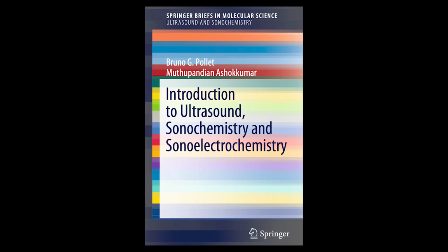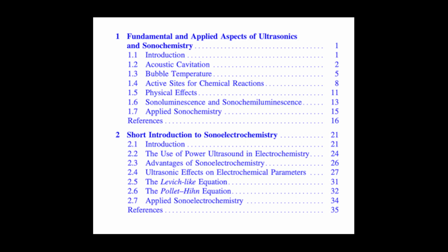For example, in studies of single-bubble sonoluminescence, SBSL, where scientists managed to trap and study just one stable, oscillating bubble, the temperature estimates can be truly extreme. They analyze the spectrum of the light emitted when that single bubble collapses, fitting it to a black-body radiation curve. The estimates there range from around 5,000 K, consistent with the basic theory, all the way up to, well, some estimates go above 50,000 K.